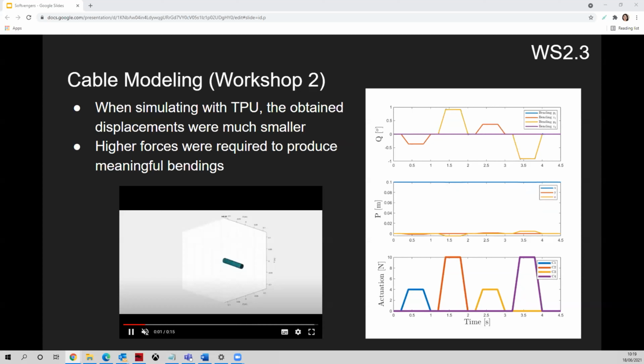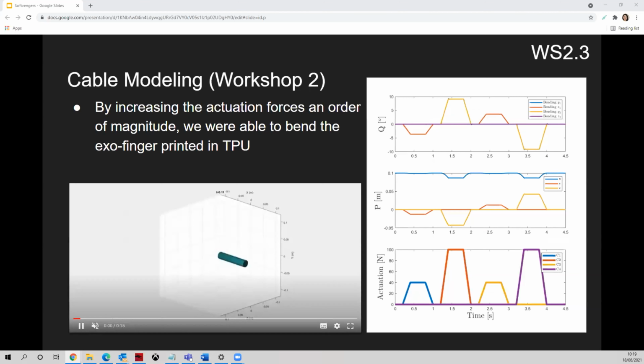The same simulation was then carried out, but with a change to the exofinger material. Specifically, TPU was used, and the same actuation forces were applied to the cable. In the simulation, though, as you can see, the exoskeleton finger is not bending, and this is because of the increased stiffness in the material. However, as shown here, the finger was able to be actuated with increased forces, though as a result, this would require increased motor torque or stronger actuation and could increase the weight of the solution.